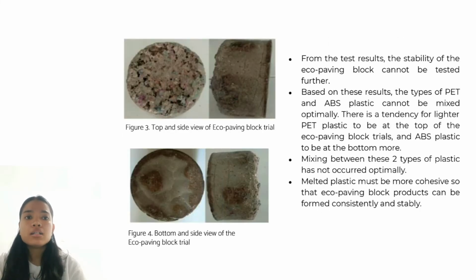Next, here is a picture of the top and side view of the eco-paving block trial. From the test result, the stability of the eco-paving block cannot be tested further. Based on the result, the types of PET and ABS plastic cannot be mixed optimally. There is a tendency for the lighter PET plastic to be at the top of the eco-paving block trials and ABS plastic to be at the bottom. Mixing between these two types of plastic has not occurred optimally. The melted plastic must be more cohesive so that the eco-paving block product can be formed consistently and stable.